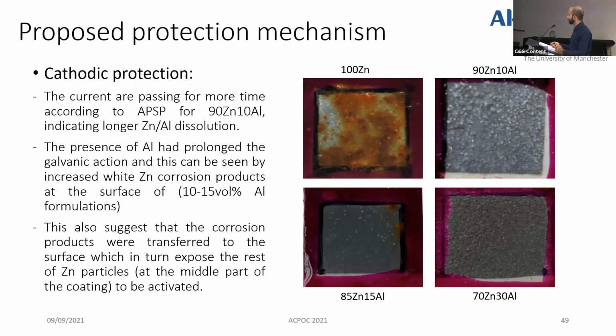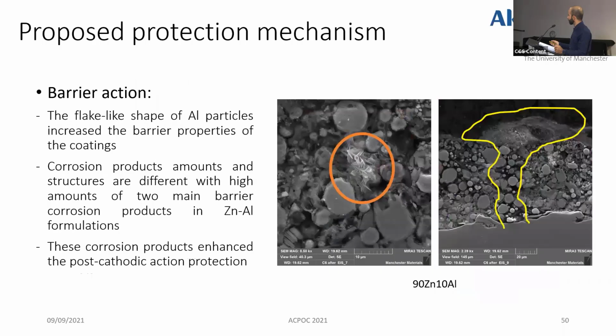zinc-aluminum dissolution, and the presence of aluminum prolongs the galvanic action. This can be seen by increased zinc corrosion products in these two coatings here. This also suggests that corrosion products are transferred to the surface, as can be seen in the SEM image, which exposes the rest of the zinc particles to offer some more galvanic action.